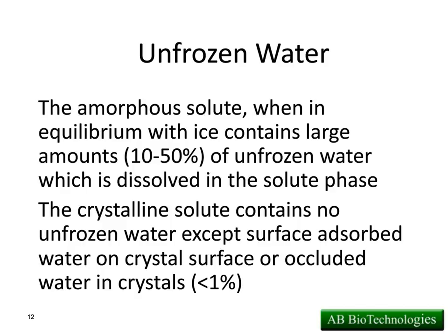Now, we've got to get it out, and it's during secondary drying that we drive that out. But it is unfrozen water, and how we approach our secondary drying is absolutely critical on understanding what we have. For crystalline solutes, we may have some unfrozen water, but it's just going to be one or two molecules loosely associated with the surface of the crystals. So at the end of primary drying, if you've got a completely crystalline formulation, it's already going to be 99.99% dry. I've developed cycles where we have not even used a secondary drying protocol because primary drying was enough to get it dry and meet our spec. That's not going to be the case with an amorphous formulation.